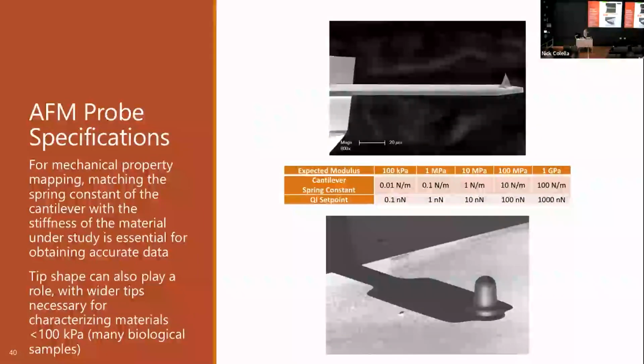That's what this slide's all about. We can have sharp probes that have a very sharp tip. These are more traditional AFM probes, so these are good for indenting into some stiffer materials. If you have soft materials like lots of biological tissue, hydrogels, et cetera, you might need a more broad probe where we're distributing that force over a larger area, which is less of a strain on the sample. But depending on what material you have, you'll need to choose an appropriate cantilever to get good data.